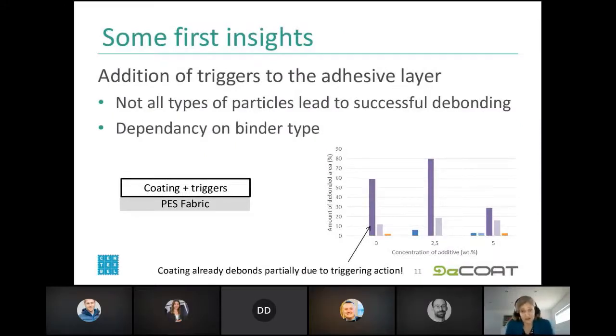When we look at some first insights, the first way is that we added the triggers to the coating layer, so to the adhesive layers. For example, here we had a polyester fabric with a top coat with triggers inside. What we can already say right now is that not all types of particles lead to successful debonding, and we also see a huge dependency on the binder type.